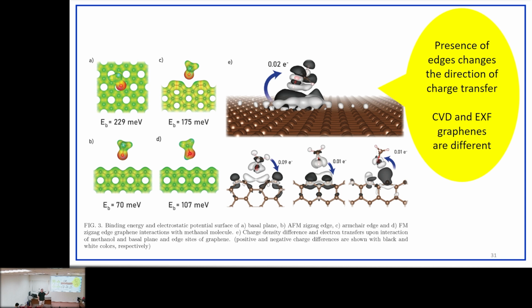After using this technique, first of all, we tested the sensitivity of the calculations by placing molecules at different points. So at every point, at every side of the edge, we see the same behavior. You are correct. Every DFT calculation is a kind of approach, so the numbers are not exact, but the tendency is always like this. The number 0.09 can change if the molecule is here. It can be 0.07, 0.05, but the tendency is not changing.